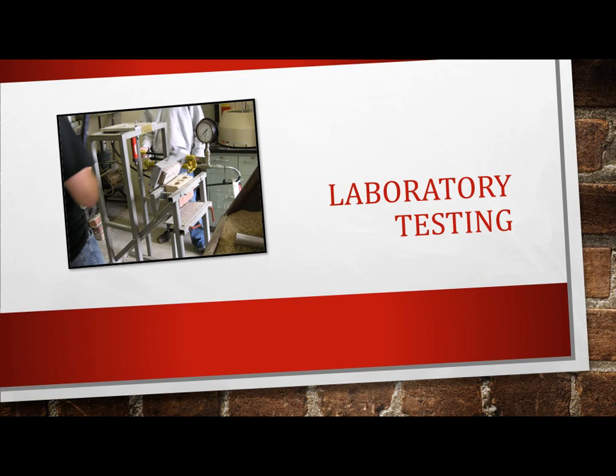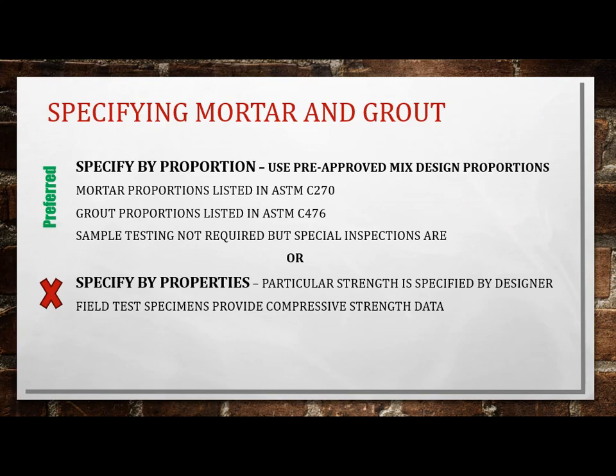I will cover some laboratory testing techniques here. And just a quick note, I'm going to show how to test mortar and grout in field testing, but a lot of times field testing of mortar and grout is not done, it's not required that often. It's kind of been eliminated from a lot of specifications, but instead you specify by proportion. And what that means is in C270, for mortar, there are approved mix designs, through empirical data, kind of like approved concrete mix designs. There are approved mortar mix designs, and approved grout mix designs. So if you select these proportions, you buy the pre-blended mixture, have a silo, you do not have to make the test samples. You still have to do inspections, but the test samples would not be required.